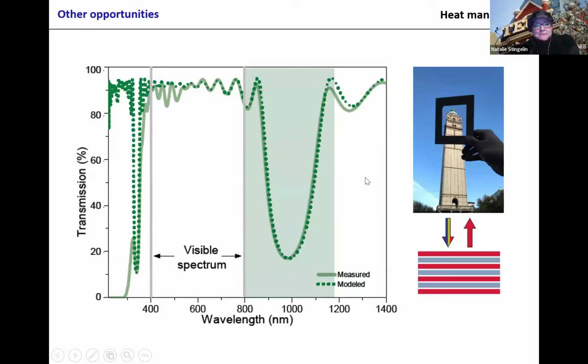You shift this, but where you have to be a bit careful is what you see here in the dotted line, the calculation, which is hidden here in the measurement, the solid line. Eventually, similar to X-ray diffraction or optics, this is the first order reflection, and this is the second order reflection. So what you have to be careful of is if you shift this one too much, eventually you will shift this second order, this very sharp peak, into the visible.